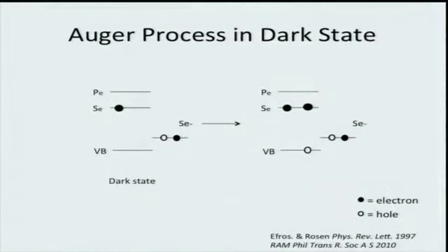When you have this as a dark period, you can see why it's dark from this thing here. There it is. Now we shine light, and let's see what happens. It rises. That's the result of the light. And what happens next? Well, it might fluoresce, but the chances are bigger, you can show, that it comes down like that. One goes down while the other goes up. That's an Auger process. And of course, that has involved no fluorescence, so it's dark.